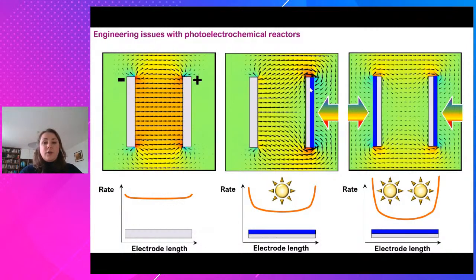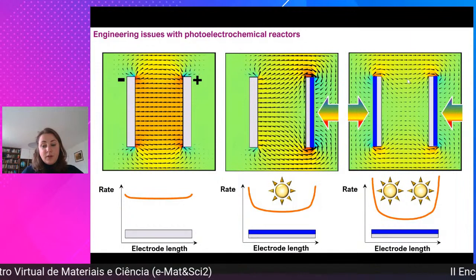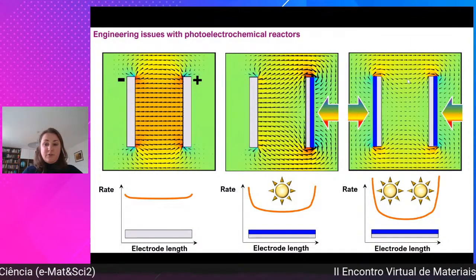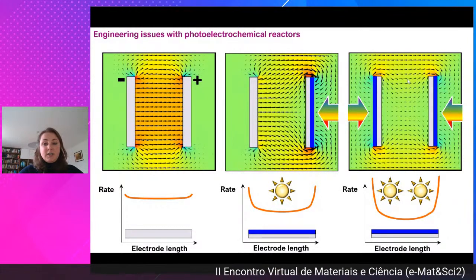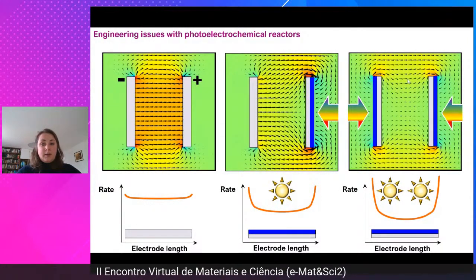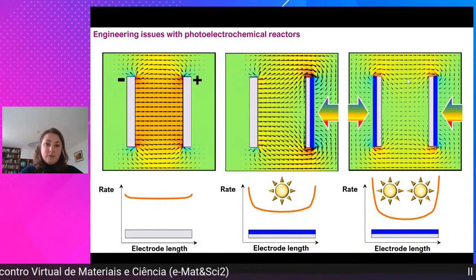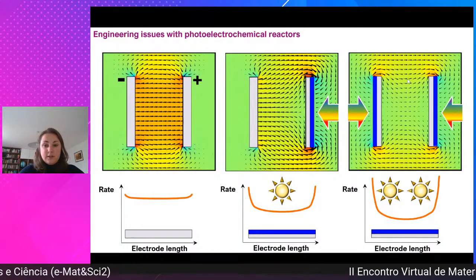So how large is the photocurrent? If this was typical electrolyzers, through which you'd normally pass something like several thousand amperes per square meter, these effects would be enormous. But the one positive thing about photoelectrolyzers not having such high currents is that these effects aren't as bad as perhaps is illustrated here. But still, you need to be able to model the photoelectrochemical kinetics at specific interfaces in order to actually predict when these effects become very pronounced and when they will start limiting reactor performance. So it really helps in the design of the reactor.